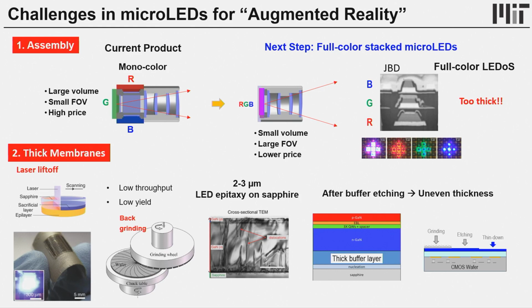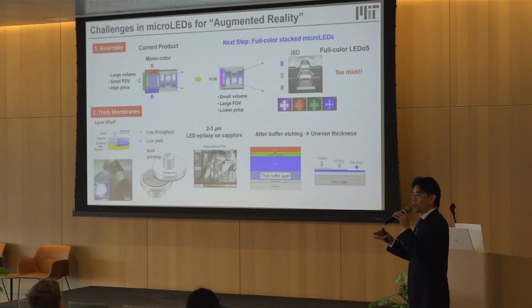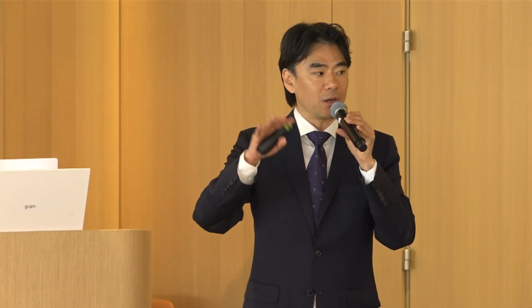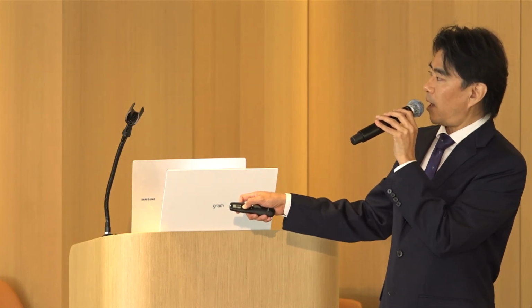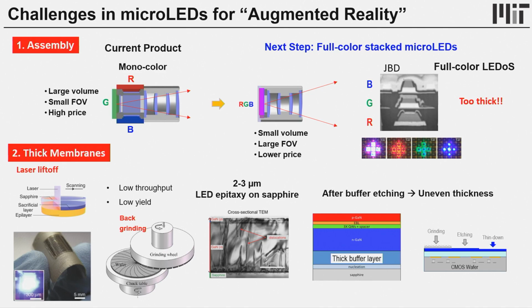So to make it thinner and to make the innovation happen, we know that we need very, very thin RGB, right? At the moment, the challenge is associated with the thick membrane that we are preparing right now. When you grow LED structures on the wafer, typically gallium nitride, indium gallium nitride, by using epitaxy, it's typically pretty thick, because we are either growing gallium nitride LEDs on silicon or gallium nitride LEDs on sapphire. Then there is a huge lattice mismatch between those. You will need to grow a pretty thick buffer layer in between. After you grow this thick buffer layer, typically the whole LED stack is 2 microns. Then you have to release it by using laser lift-off, which is known to be not very efficient, or you have to completely grind the wafer to isolate these LEDs.